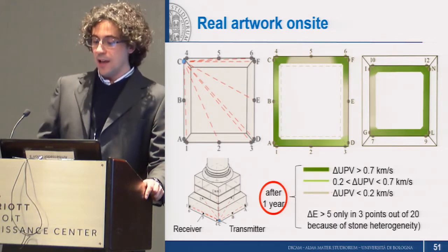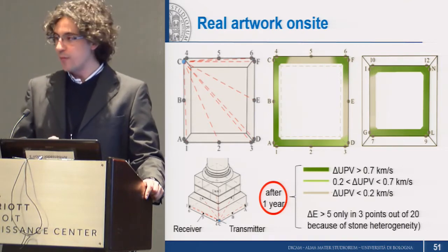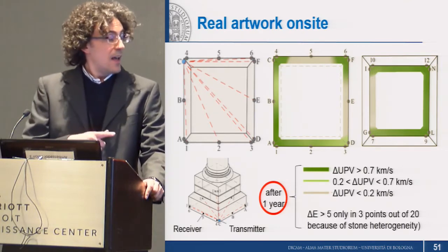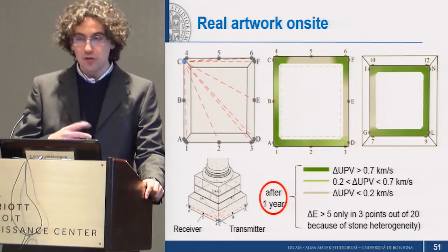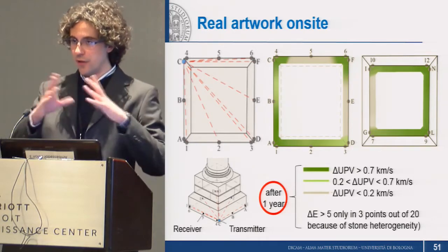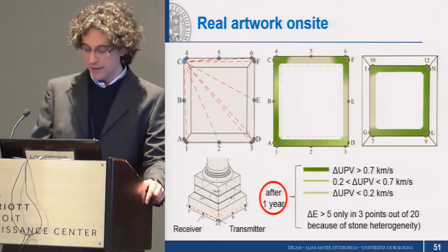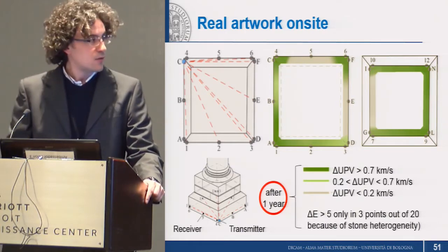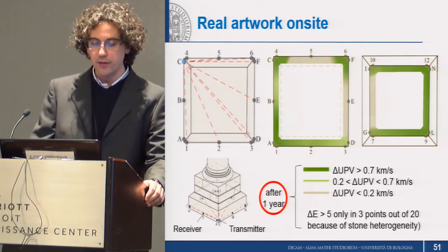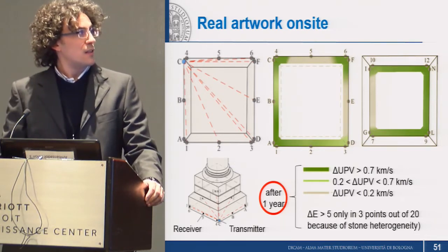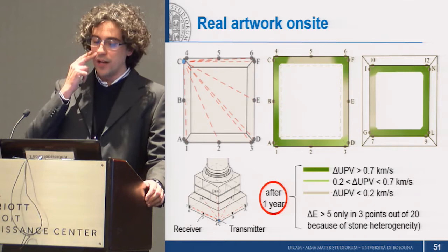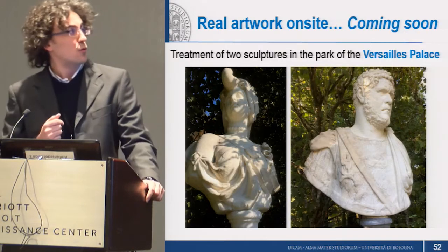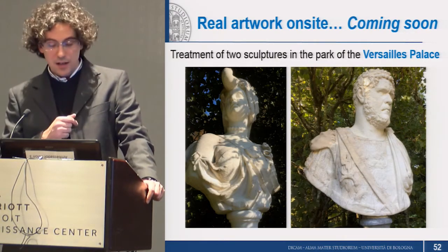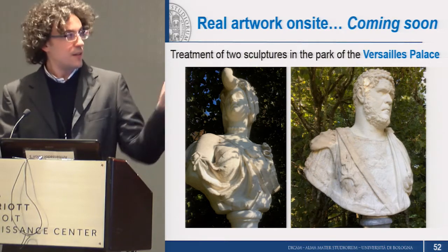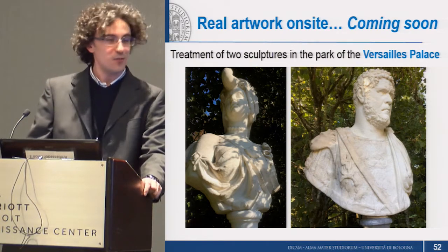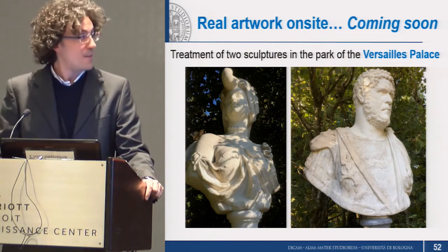So we found that still good mechanical improvement was present, and that the variation, the color change, the modification of the aesthetic appearance, was below the threshold that is usually accepted in the conservation field, which is, of course, positive. So starting from this, in the next few months, we should also carry out a couple of pilot applications to real sculptures in the Versailles Palace in France. So these are the two lucky candidates that are going to be treated, so hopefully we won't spoil them.